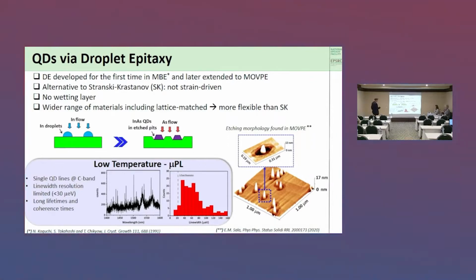By MOVPE, we're investigating a different process. This is the technique of droplet epitaxy. And in that case, it's simpler. So we have a substrate, we apply indium metal, and again, through surface tension and reduction of energy, at some point the indium forms droplets on the surface, and then we expose those droplets to arsenic, and the droplets are converted into indium arsenide quantum dots. So it's an alternative to Stranski-Krastanov. It is not a strain-driven process as it is in the indium arsenide case, and that gives you various advantages.